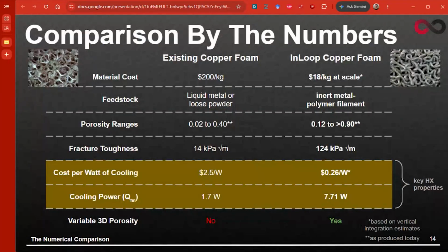When we looked at the existing metal foam market, we found that it's a low supply and growing demand. And that kind of market, existing players can charge a lot. Existing copper metal foam sells for up to $200 per kilogram. And we did a techno-economic model of our foam and found that we can serve that material for far less.